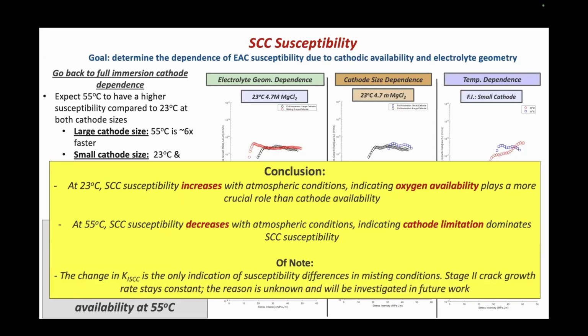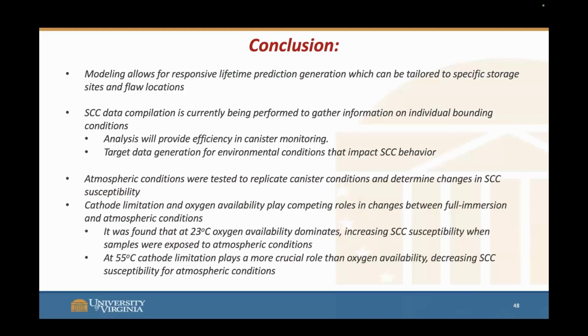One of the notes is that this research is still ongoing because I'm still doing my PhD. One of the things we don't understand is why only really the K1SCC has been affected, so the stress corrosion cracking initiation. We don't really understand why stage 2 crack growth rates aren't super affected when it comes to atmospheric versus misting conditions. We're hoping to investigate this with future work. If anyone has ideas, I'm open to suggestions. And with that, those are the conclusions. I'm going to leave them up because I probably went pretty long.